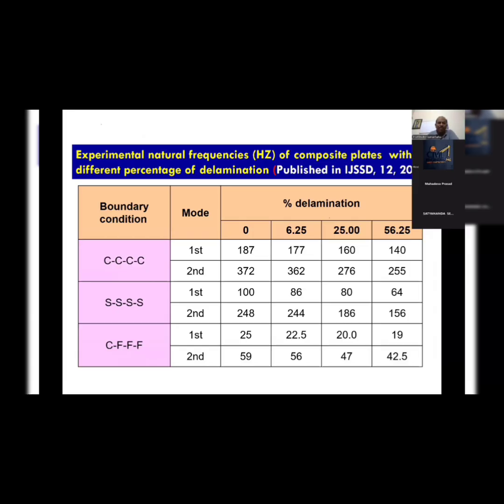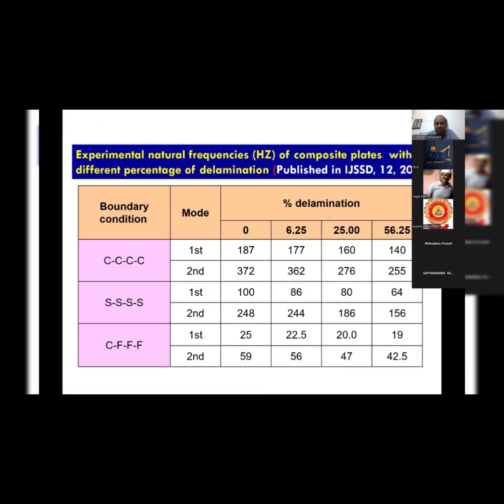This is delamination. As you increase the delamination, the frequencies decrease, whether it is for clamped, simply supported or cantilever. This is the first mode, this is the second mode, and every time with increase of delamination, the frequencies decrease. Delamination means it's a defect. Due to the defect, naturally it is supposed to decrease the stiffness, a reduction of the stiffness.